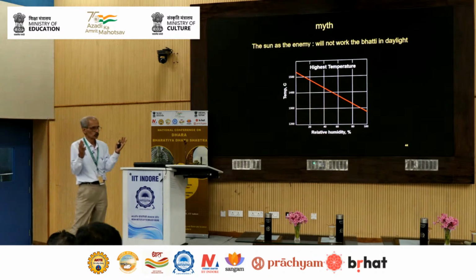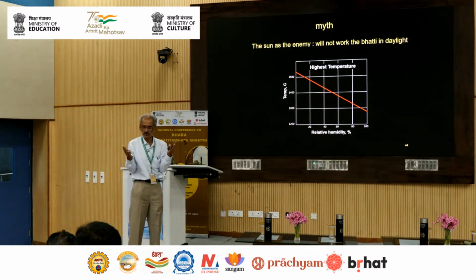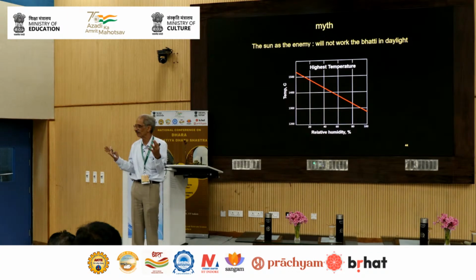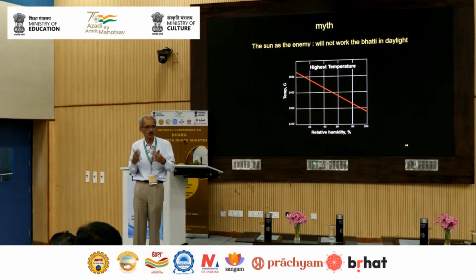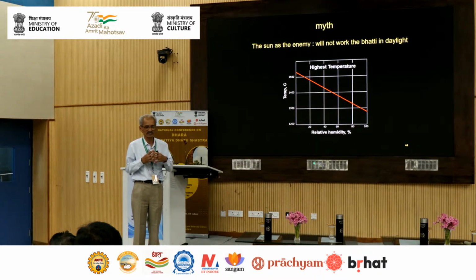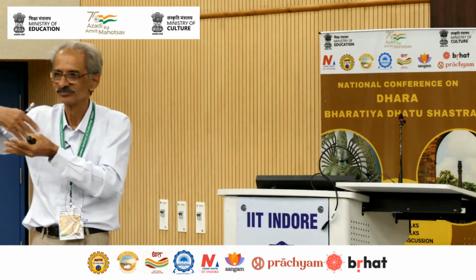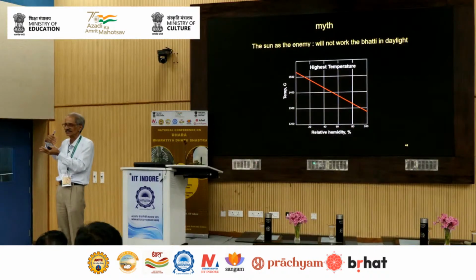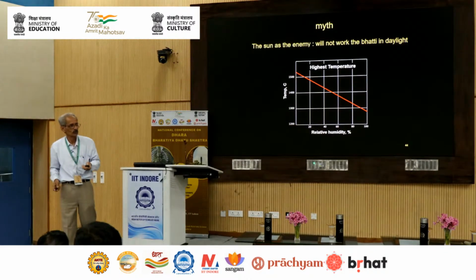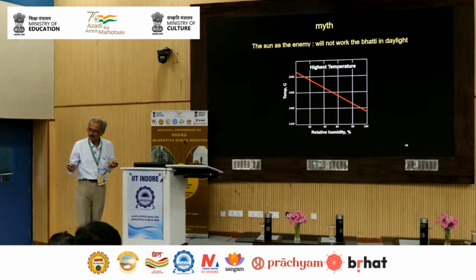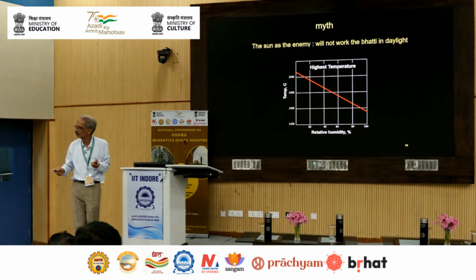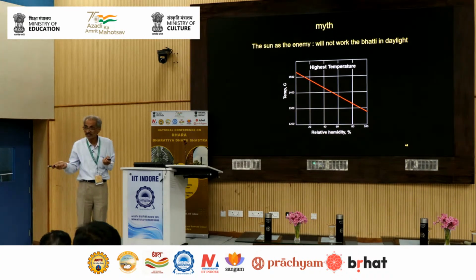And anybody who has done some raceway flame temperature calculation for blast furnaces knows that the temperature that you get from an air-blown flame, in a charcoal furnace or a coal furnace, is dependent on moisture. For example, in the blast furnace, if he wants to decrease the temperature, he will humidify the blast. You dry the blast, and then you get higher temperature. So if they want the highest temperature, that is the time to finish, just before sunrise. That is why they work in the night.